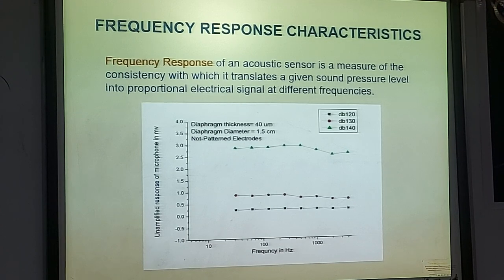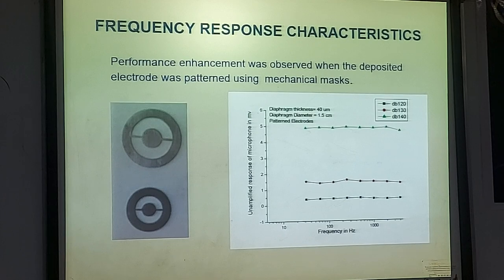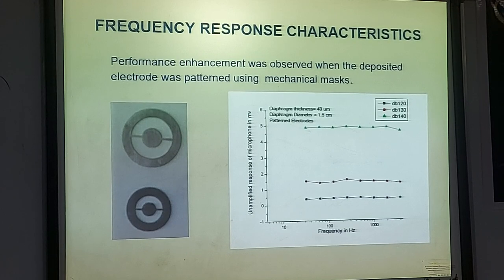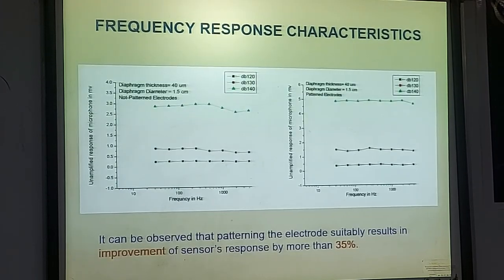120 dB now, which is shown in the dark color. Other ones 130 and 140. So you can see that the response is almost flat, uniform. And then we also did this with a segmented electrode arrangement, and we got an enhancement of signal of about 30%. So this is a comparison of the same. I will not go into the detail. What we found was that a suitable pattern in the electrode results in improvement of sensor response by about 35%.